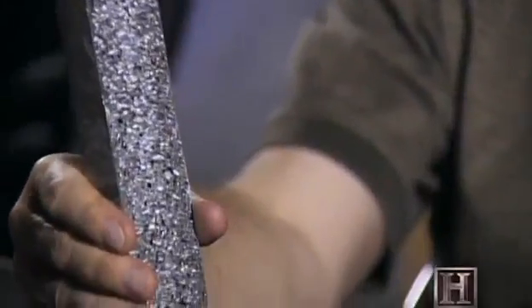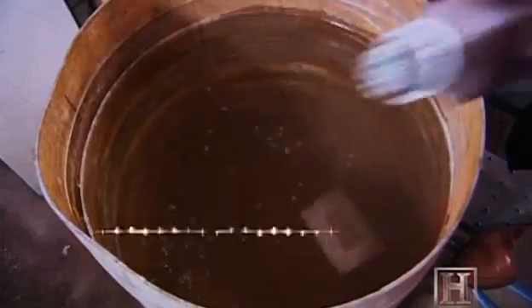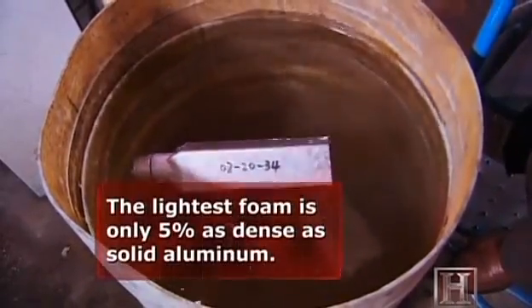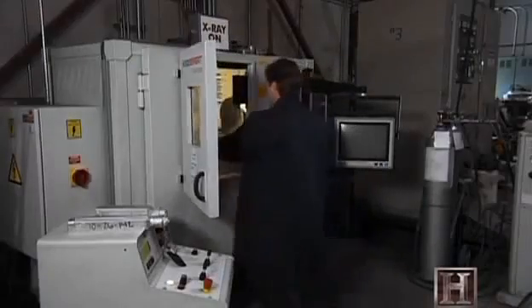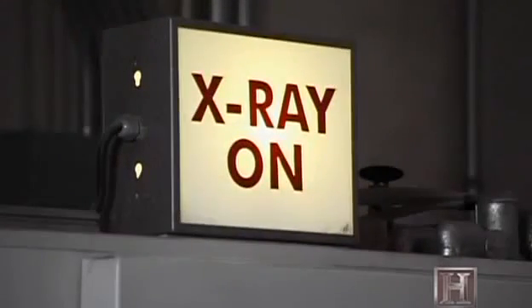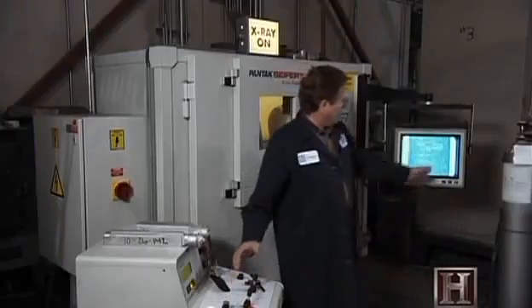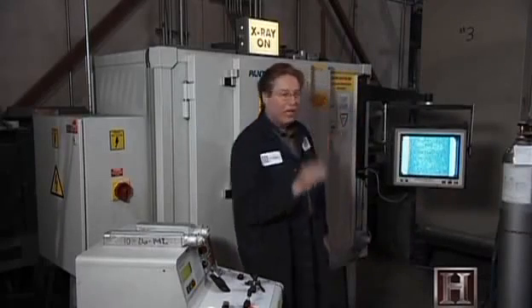Foamed aluminum can also be injected into a three-dimensional cast. What looks like a heavy chunk of metal is actually light enough to float in water. A view of the casting skeleton shows why. In the X-ray machine, we have a part that from the outside looks like a solid aluminum casting. We're looking right on the edge of the part. You can see a dark line here where we're actually looking down the edge of the casting. But if I rotate this, you can see the cellular structure. There's a lot more air there than there is solid material. The cellular structure allows it to collapse and absorb energy. Imagine each one of these little bubbles is breaking, these cells is breaking as the part is crushed, and there's energy being absorbed by every one of those walls collapsing.